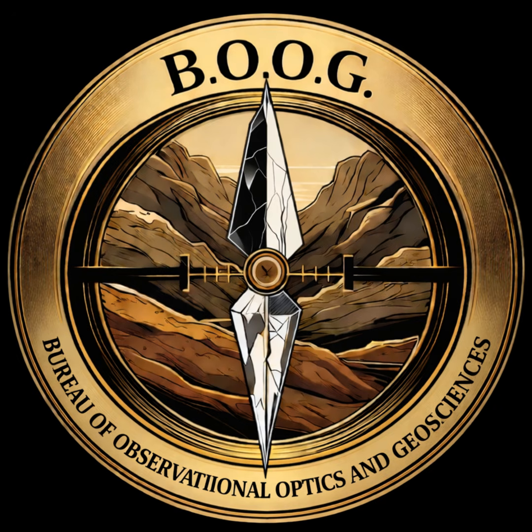Unbelievable. And the mind-blowing part is that the physical size of the particle strictly dictates the color your eye perceives. When the exsolved metallic copper nanoparticles are extremely small, specifically under 80 nanometers in diameter, they trigger a phenomenon called surface plasmon resonance. Okay, I read up on surface plasmon resonance, and I want to try and translate this into everyday terms for a second.